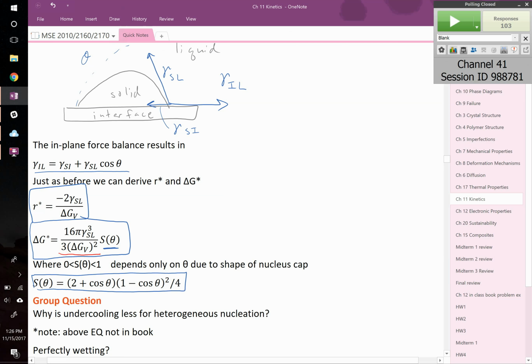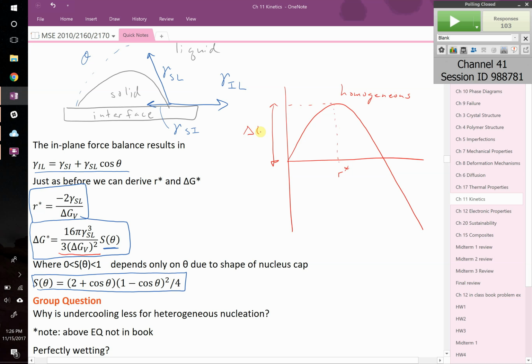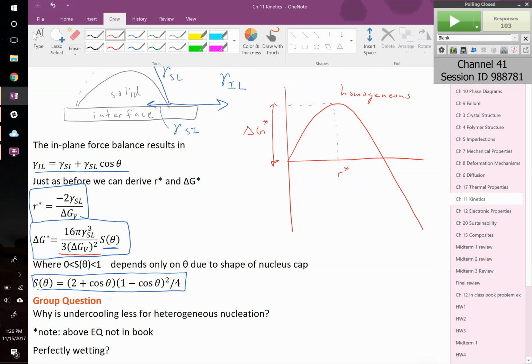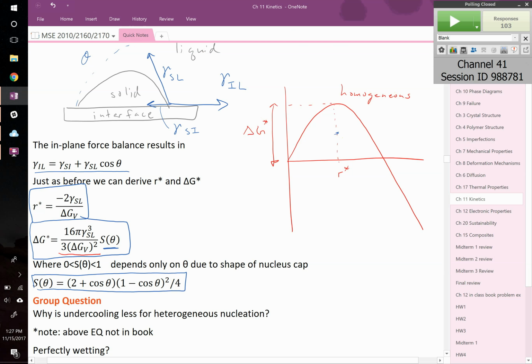So graphically, what does that look like? It looks like this. Here's our homogeneous case. It had some point r star, and it had some height over here. We call this distance delta g star for homogeneous. Now we're modifying that, and we're going to have the same r star, but something smaller in terms of activation energy. So it might look something like this. That distance right there is that guy.